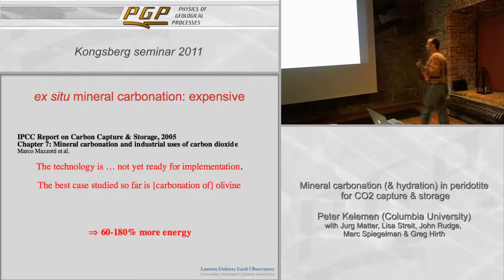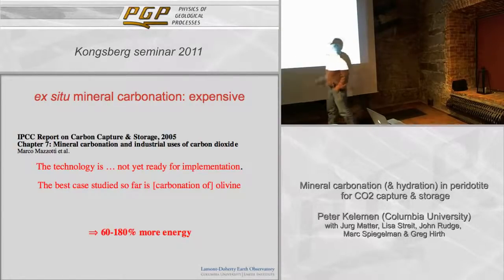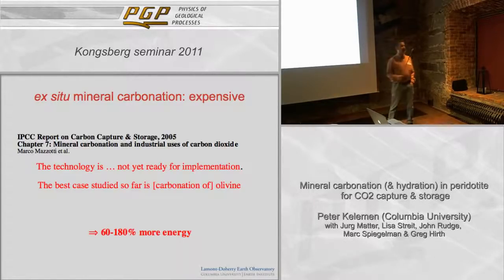Okay, but one of the primary proponents of this is Marco Mazzotti in Zurich. And he's the lead author on the chapter in the IPCC report on mineral carbonation, and he says it's not ready for prime time. What these guys have in mind is they quarry olivine someplace, bring it to the power plant, grind it up, build a pressure vessel, put the olivine in the pressure vessel, keep the temperature high with a lot of pressure, take CO2 from the power plant, put it in the bottom, and carbonate olivine. And that process, as you might expect, about doubles the energy requirement for a given output from the power plant.